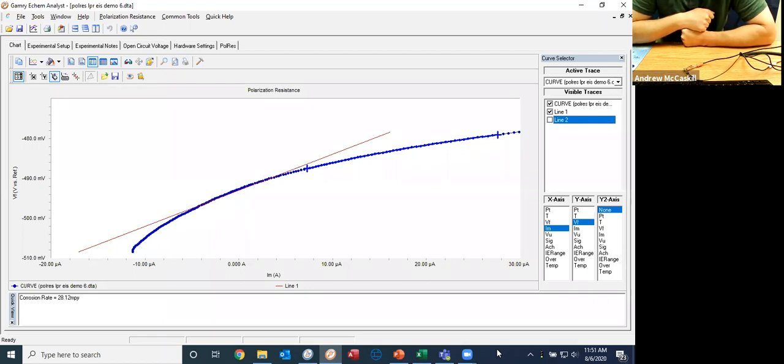With a potentiodynamic scan, where you're going 1 or 2 volts, you certainly are modifying the surface, but that's what you're trying to do. You're trying to pull out information due to that. In an LPR experiment, you don't want to cause a vast change in the material. You just want to perturb the system enough so you can figure out what that I corr value is. So it's a very small perturbation just so you can tease out what that RP value is to get the I corr. So is LPR destructive?